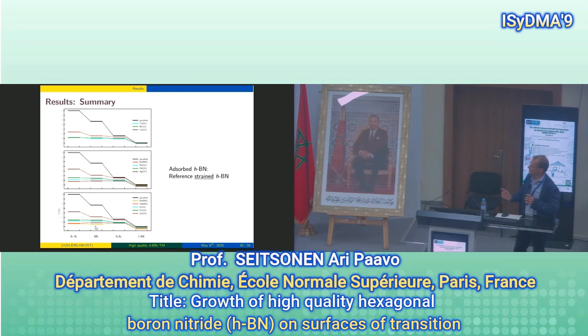And one sees the main message here: depending on the substrate, you have different binding energy of the atoms with respect to the dimers or hexamers. And in some cases, you even go up in energy to form the dimer on the surface. So then we expect, of course, that the initial growth is slow on this kind of substrate.